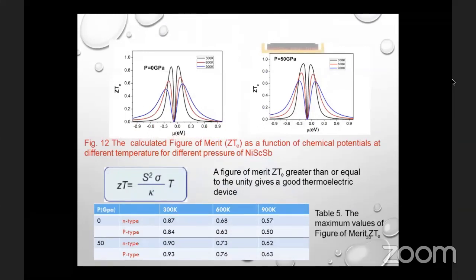For a thermoelectric device, the efficiency of a material can be determined by the dimensionless figure of merit. Again, you can see the formula. A figure of merit ZT greater than or equal to 1 gives a good thermoelectric device. Figure 12 shows the ZT curves of this compound as a function of chemical potential at different temperatures and different pressures.